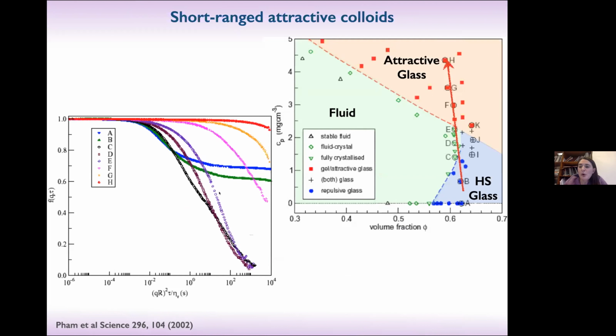So doing the dynamic scattering experiments from point A to H along this red arrow, this famous paper showed that the dynamics is actually reentrant. You start from hard sphere samples, the A point that is well arrested, similarly to the curve of Van Megen that you saw in the first slide. You start to increase polymer concentration, this goes down, then you increase it a bit more, it goes completely down, so you lose completely ergodicity, you lose also the two-step.